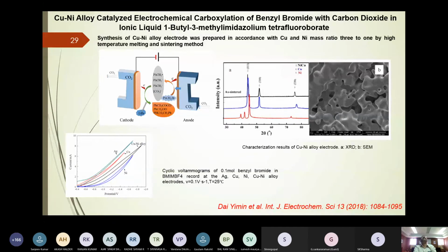Here you can see the copper nickel alloy formation by a simple chemical method, by applying high temperature followed by sintering. Here the SEM shows the sizes of the copper nickel alloy nanoparticles, followed by XRD. XRD shows the presence of copper nickel. As usual, voltammetry shows the higher current density for its catalytic behavior in BMI BF4 ionic liquid.